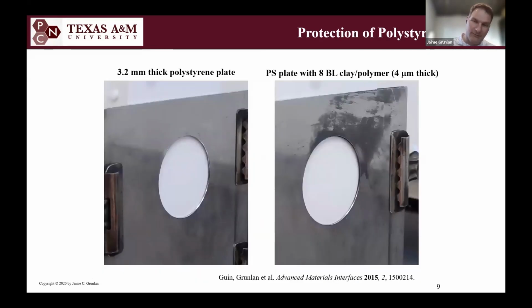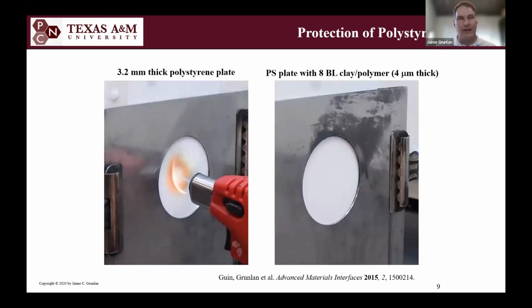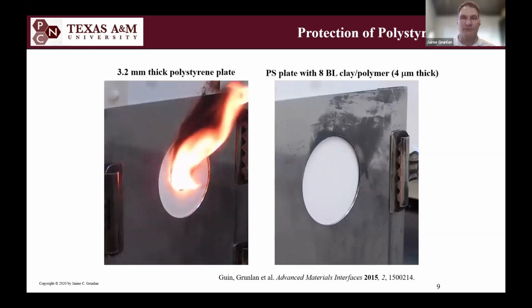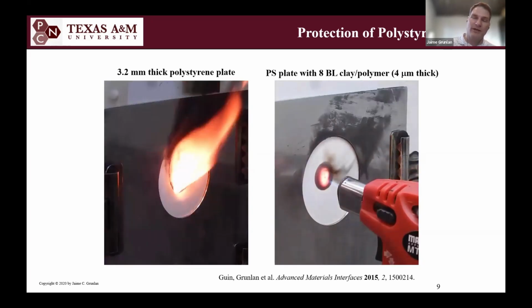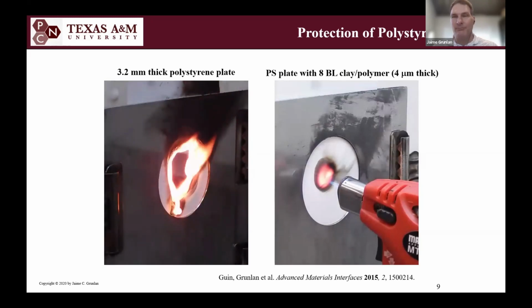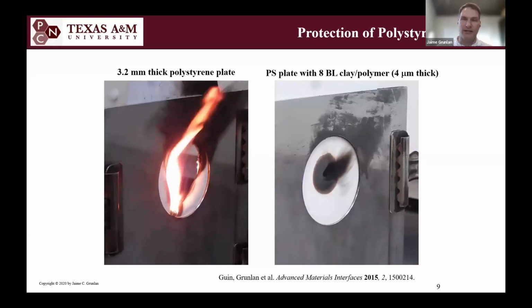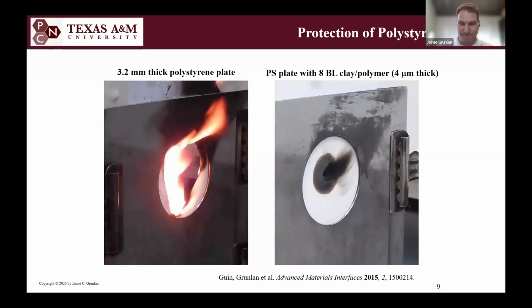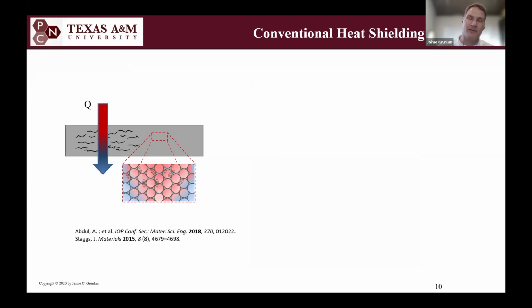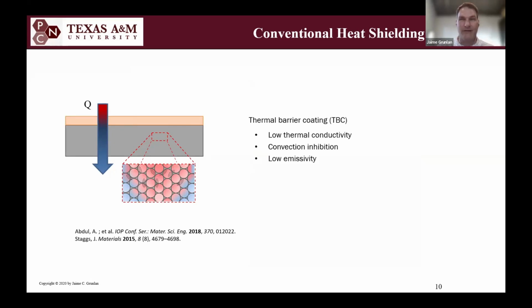This same coating I can deposit onto a 3 millimeter thick polystyrene plate. Think of this as IKEA furniture, mimic, you could say. A polystyrene plate with no coating on it is, of course, very flammable. So this is a little household butane torch that we bought at Home Depot. And then we have that 4 micron thick 8 bilayer clay polymer coating, the chitosan with vermiculite. You can hold a torch on there for 15 minutes and you won't ignite that polystyrene plate. We can debate whether that means it's flame retardant or if it's just heat shielding. But with that heat shielding idea in mind, we decided to look more deeply into this kind of coating.